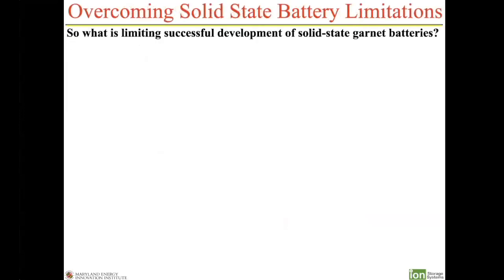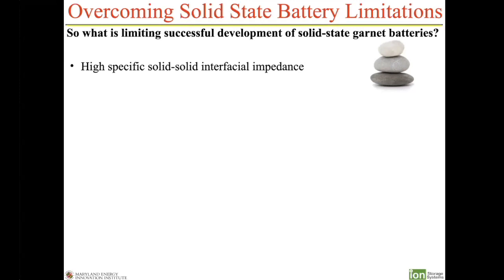So what's been limiting the successful development of solid-state garnet batteries since they have all of these wonderful advantages? One is a high specific solid-solid interfacial impedance. And you can think about it by stacking stones on top of each other, right? You have a gap between them. How do you get a uniform, atomic-level interface between two dissimilar materials?